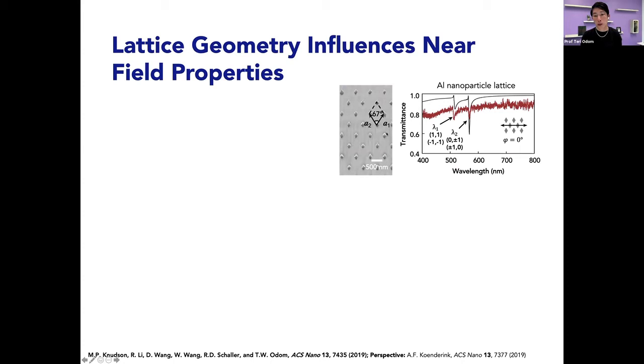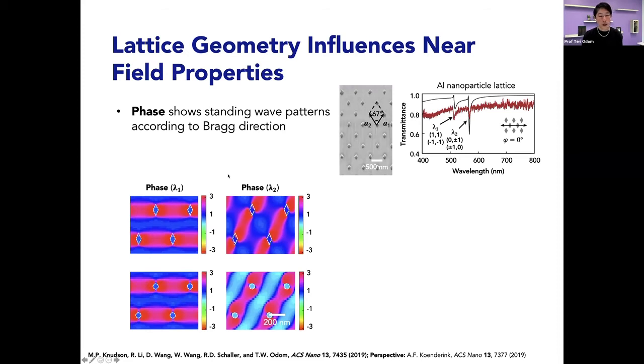Okay, so in this type of geometry, these are the basis vectors. These are aluminum nanoparticle lattices. If the polarization is in this direction, you notice that there are two SLRs at two different wavelengths, and these are coming from different coupling to different Bragg modes. So either the 0-1 mode, 1-0, these are degenerate at this point, or a 1-1 mode. And so if we look at the phase maps, we can see that at the shorter wavelength, you have a standing wave mode in this direction that corresponds to this. We just rotated the basis. And in this case, you have a standing wave mode in this direction according to the 1-1.